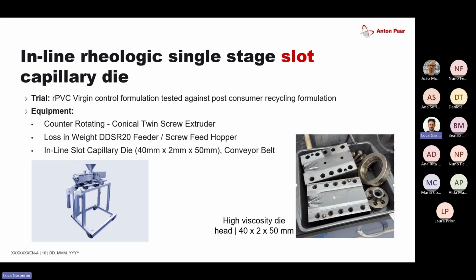So for PVC applications, for average rheological measurements, usually a single screw extruder is used. But for PVC, we often use the conical twin screw extruder, because PVC is a very shear sensitive material and it works a little bit better in the conical. Within the conical, we also have the option to measure a normalized pressure profile, which was developed in cooperation with a customer of ours, which allows us to be a bit more independent from the screw speed in the viscosity measurements.